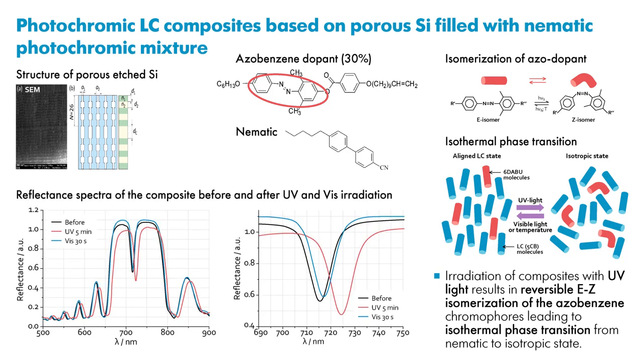Here, the reflectance spectra of the composite before and after irradiation are shown. UV radiation causes the redshift of the photonic bandgap and cavity mode by about 10 nanometers. This shift is associated with the increasing of the effective refractive index of the composite. Such increase of the refractive index can be explained if we assume that liquid crystalline molecules before irradiation are aligned along the axis of the pores. After UV irradiation and transition to isotropic state, the refractive index slightly increases, resulting in redshift of photonic bandgap position.